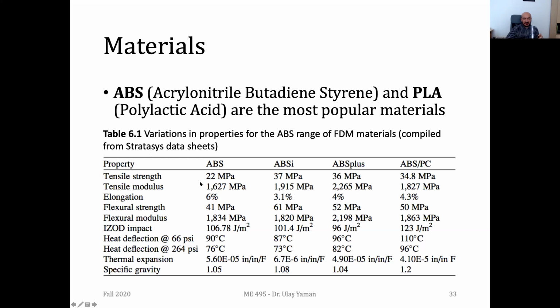And here are some typical values from Stratasys company. The tensile strength, tensile modulus, and the elongation are usually around, as you see. But depending on some variations of ABS material, it might be from 3% to 6%. And the heat deflection, as you see, usually around 70 degrees, it starts bending, so you cannot retain its shape after 70 degrees.